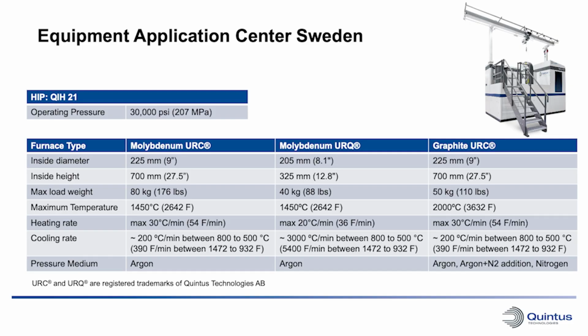So the larger HIP equipment that you have in the application center is quite sizable, but can the same machine handle different furnaces, or is it just one machine per furnace? No, the same machine can use different furnaces. So we have three different ones. Two of them are made of molybdenum and can handle a temperature up to 1450 degrees Celsius. And one made of graphite, and that can go up to 2000 degrees Celsius.